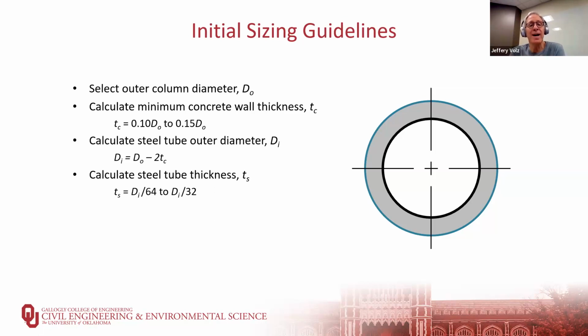It's important to recognize that the benefit of that concrete core is it reduces the tendency of that steel tube to buckle and the FRP tube to buckle. And we'll talk about that during our actual test. So again, all three of these materials help each other. The steel and the FRP act as stay-in-place forms. The steel provides the ductility, the FRP provides the protection and the durability. They provide confinement to the concrete, and the concrete prevents local buckling and global buckling of the steel tube.